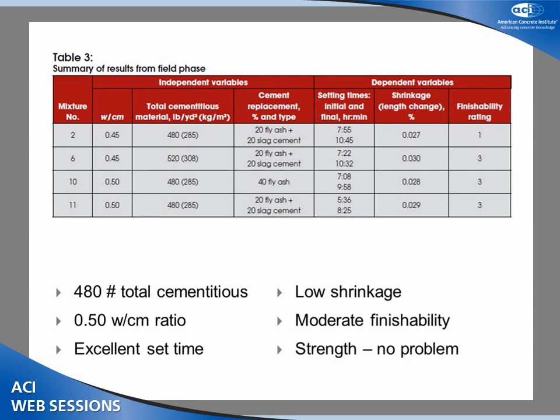Well, frankly, on the basis of this research, I'm going to probably raise my specs to that 0.45 to 0.50. I've had them at 0.45. And I've been convinced that going to 0.50 really does help, and it helps dramatically. It seemed to help on the set time. That is very close to straight Portland cement set time by giving it a little extra water. It's akin to Dr. White's approach of internal curing, giving it more water to hydrate and more thorough curing, and it really does seem to help that set time as well. So that was an eye-opener, and it really got my attention. And again, the finishability was moderate, very low shrinkage, and it was a beautiful mix.